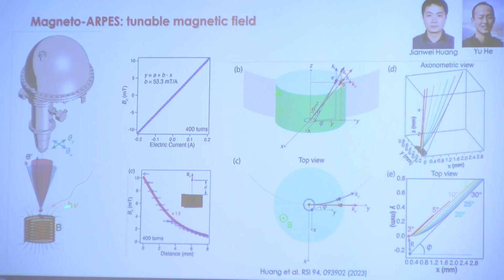He can also measure the decay of the field above the sample. We have to understand the extrinsic effects on our photoelectrons before we look for real physics. That means we need to understand what actually happens in this region, which defines the extrinsic effects on our photoelectrons. So he did a lot of finite element simulations, trying to understand the extrinsic effects on the photoelectrons emitted. If we can have a grasp on those, then we can back out the effect on the electronic state before the electrons were ejected.